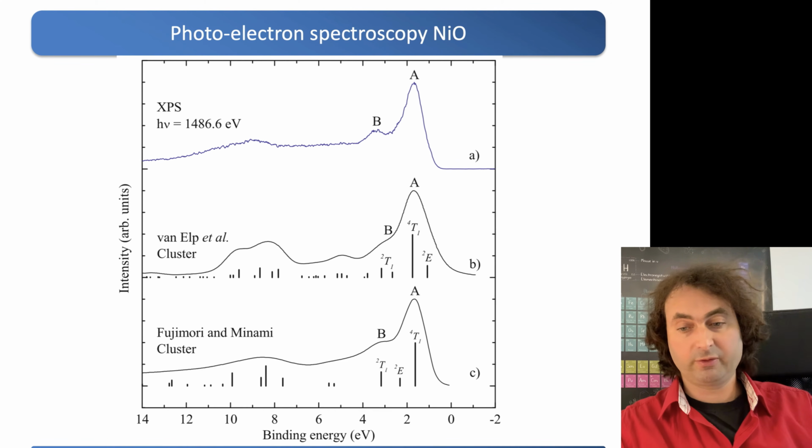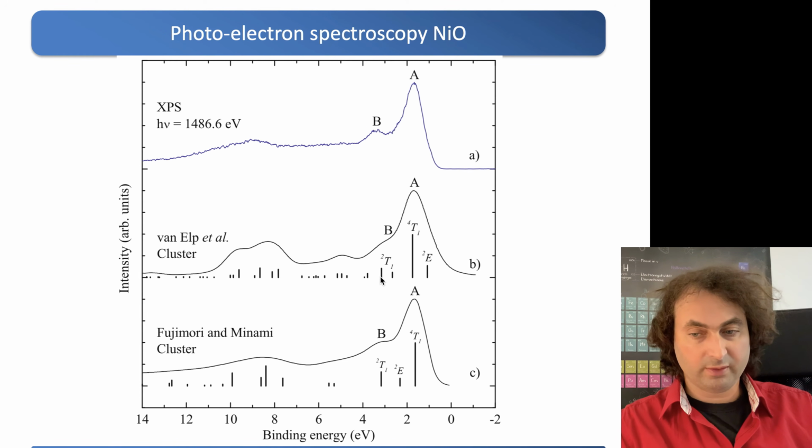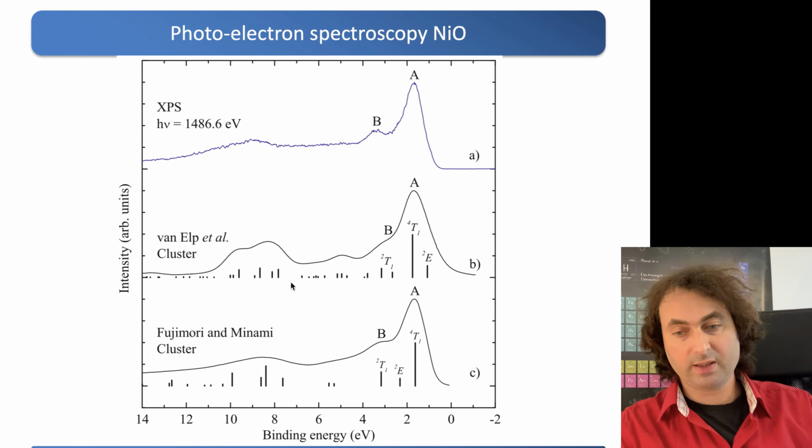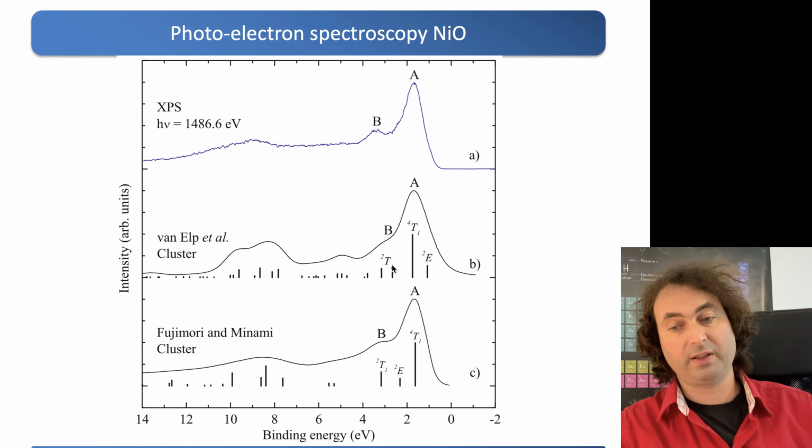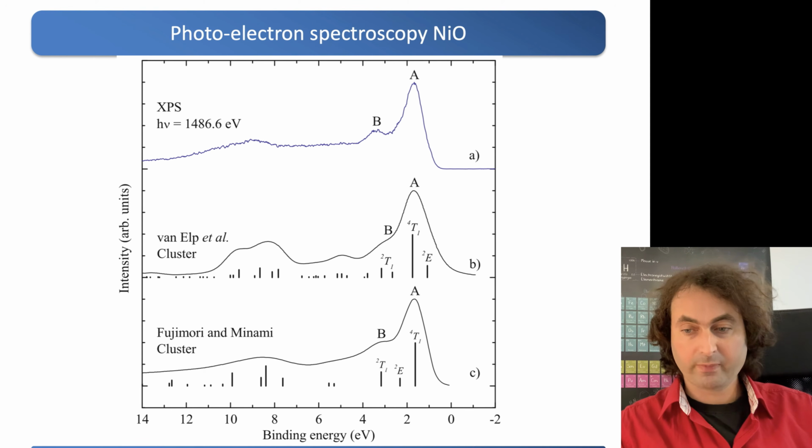Now if we go to a ligand field theory calculation or a cluster calculation, then you get a discrete set of states, and those are the discrete set of states indicated here below that belong to different atomic terms that are further split by the ligand field. And now we get the local set of d orbitals where we have the excitation as well as the charge transfer excitations, and we see that at least you get a rough understanding of where your peaks are.